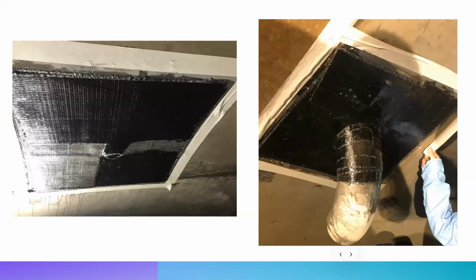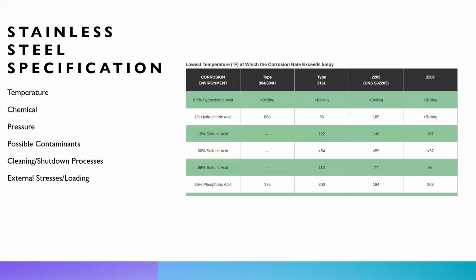If we can get it from the inside, we'll put any sort of reinforced repair that can hold pressure. So it's forming a wall on the inside of your vessel or your tank that's going to allow it to hold the pressure. It also has to be chemically resistant to the system. So this was top coated with an additional top coat to add some chemical resistance. But basically what we're doing is isolating that stainless steel from the environment to prevent that chloride cracking from occurring anymore.